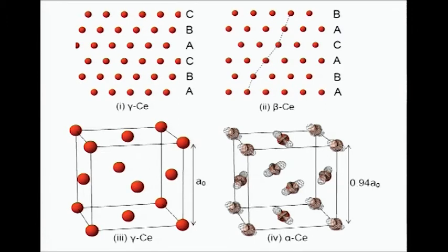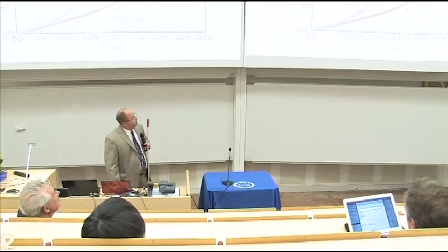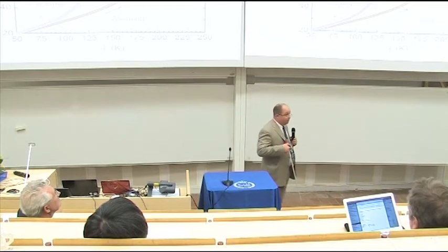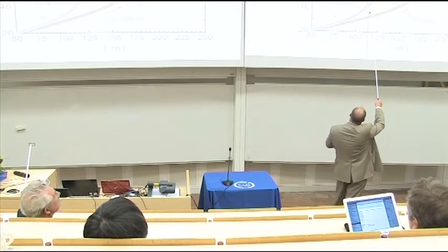So this is the best picture we have of cerium now. In order to detect the beta phase, we've used a technique that we adapted from the shape memory materials. If you just measure the resistivity here, you can see the temperature hysteresis of the transition.